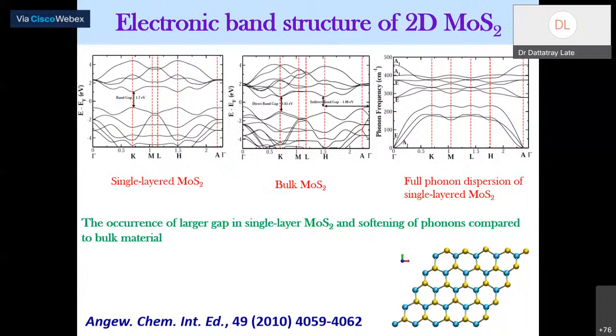For example, when you talk about the band structure of 2D MoS2, you can see the single layer of MoS2, the bulk MoS2, and the phonon dispersion of single-layer MoS2. The band gap of bulk MoS2 is near 1.2 electron volt. The moment you make one layer of MoS2, the band gap changes from 1.2 electron volt to nearly 1.6 electron volt. So depending upon the layers, you can tune the band gap of MoS2. Not only MoS2, there are many materials of this family, and the band gap can be tuned for these other materials also.